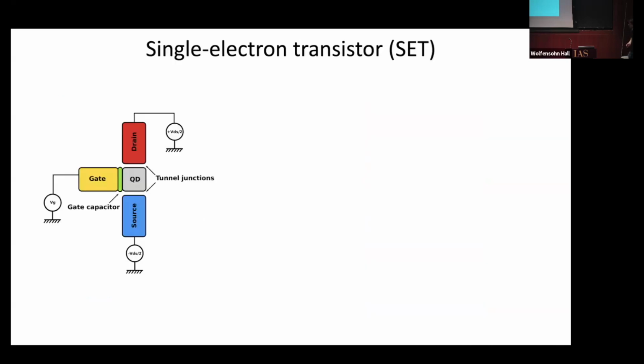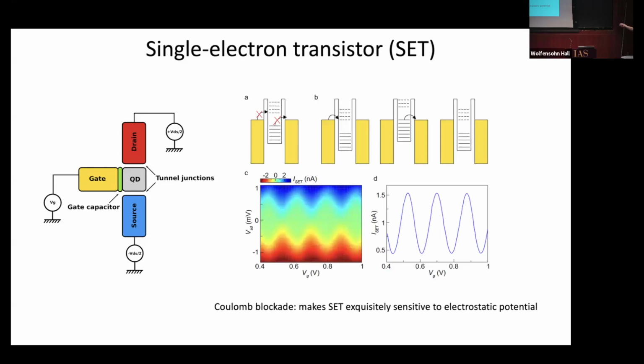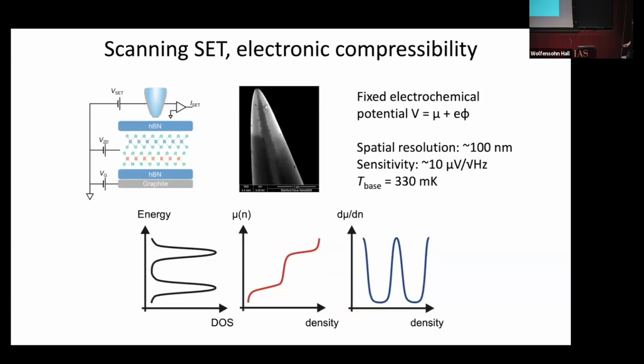So just to remind you, in case there are people who weren't at the talk yesterday or who don't remember, my group uses a particular approach using a single electron transistor as a scanning probe. Again, this is just a quantum dot or a metal island separated by source and drain electrodes. And this is a way to get Coulomb blockade physics, where as you tune the electrostatic environment of the single electron transistor, you get a modulation in the current. We can measure that and extract the nature of the local electrostatic environment. And we put this on the end of a tip.